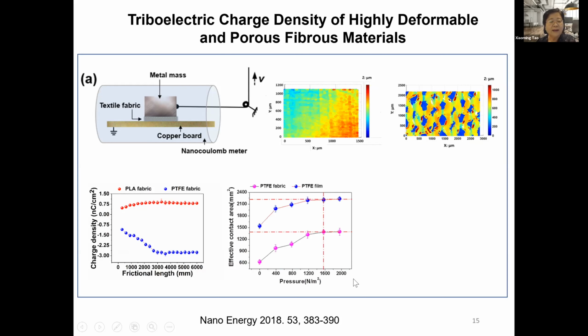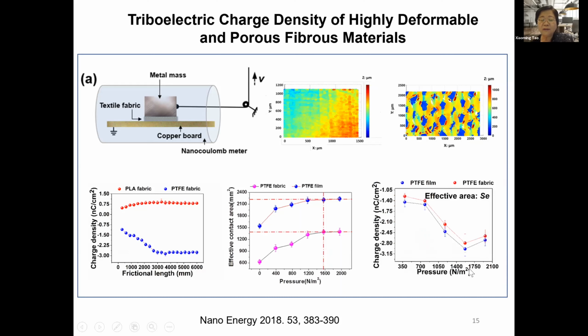And the second one, because this porous material is very soft and its roughness is in millimeters, it changes with pressure. Now, if we compress this fabric, we can see as the pressure level increases, the effective contact area actually increases, because initially there's a lot of space in the middle, and it's been squeezed. And when it reaches a certain plateau, a saturation where the material is compressed, that's what we need to get a reliable measurement. And as the contact area increases, the surface charge per unit area, of course, will change.